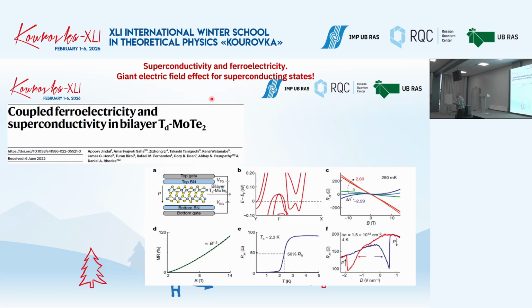And applying different voltages, they can control the ferroelectric states of these layers. And the ferroelectric ordering in such systems has some important peculiarities, which I will try to explain in a minute. Next slide. But let me just note the key point of this study. In this system, they see the superconducting resistive transition. It's the resistance as a function of temperature. And you have this resistive transition to the superconducting state.